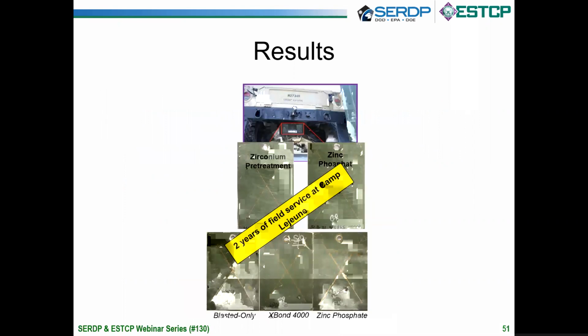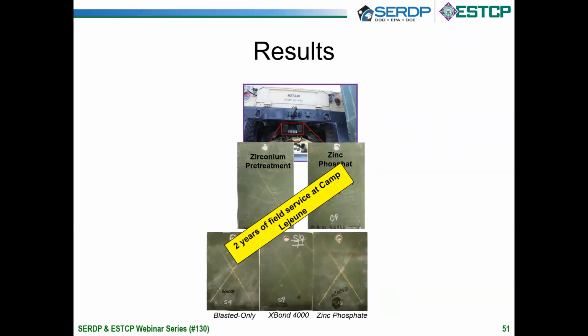And on steel, here are some test panels that are on some training vehicles down at Camp Lejeune. Performance on steel is comparable versus conventional zinc phosphate. And down below, you see the three samples: one abrasive blasted, versus X-Bond 4000, which is a zirconium pretreatment, and versus the zinc phosphate, all in very comparable condition after 2 years of exposure.